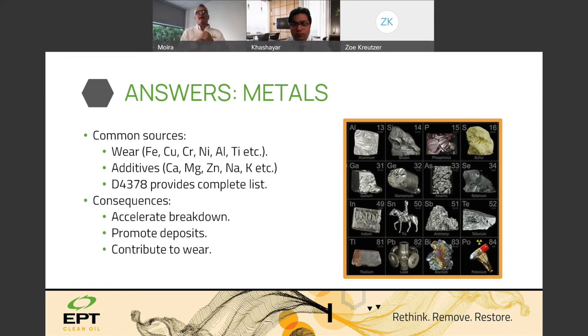Metals. In some synthetic lubricants, they're extraordinarily sensitive to metal contamination, okay? In other lubricants, less so. But it's a very simple test. It's about $14. You can do a spectrographic analysis of your system, which is like a fingerprint, and you can compare that to your new oil standard to see what contamination is increasing in your system. So I really do love this test, and I would recommend it almost for every oil application and critical machine.